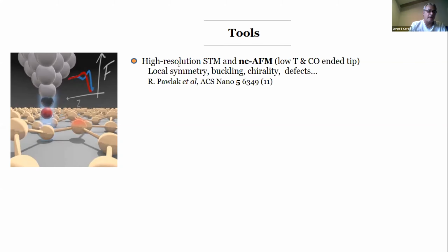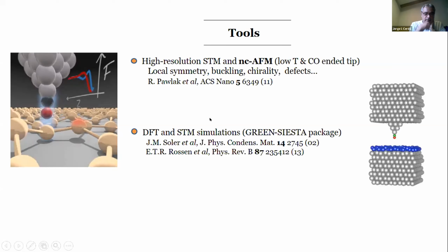The trick here is, once you have the phase you want to study on the surface, you leak a little bit of CO into the chamber, and you manage at the end to trap a CO on the tip. And this really enhances your resolution. It's very well known. But of course, you have to operate at very low temperatures. As I will try to show with this kind of tip, we can really get into very fine details of the atomic structure, like local symmetries, bucklings, chiralities, defects, especially bucklings, as I said. And still, to check that the conclusions we obtain from the AFM are correct,